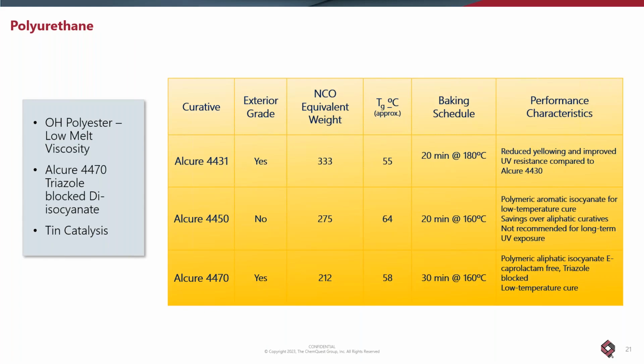Polyurethanes, when you're trying to lower the cure temperature of a polyurethane in powder coatings, urethane curing agents in powder coatings rely on a blocking agent, and basically the suppliers of the diisocyanate curing agents have alternate type blocking agents that are released in that 150 to 160 Celsius, which give you an opportunity to formulate a lower temperature cure urethane at a price, of course.